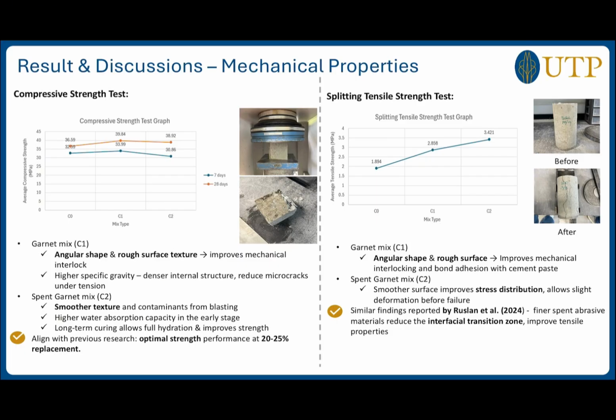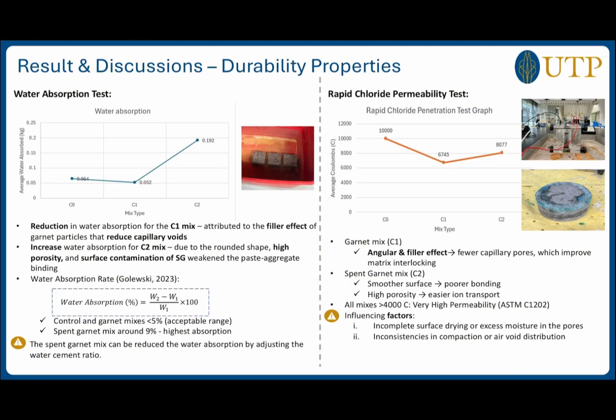For the splitting tensile strength test, the spent garnet mix has the highest tensile strength, because the smoother surface improves stress distribution, which allows slight deformation before failure. And similar findings were reported by Ruslan in 2024, where the finest spent abrasive material reduces the interfacial transition zone, which can improve tensile properties. And the last part for results and discussion is durability properties.